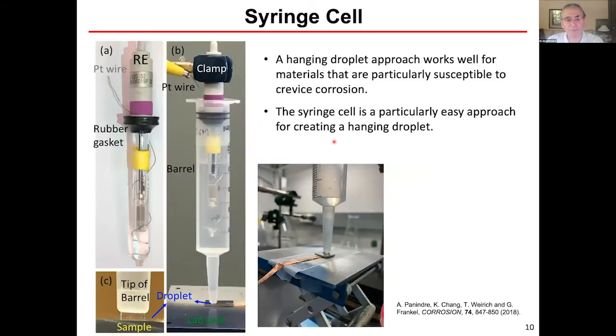One approach that we've taken is the syringe cell. John talked about a droplet cell. This is also work that was led by the efforts of Anoop and published a few years ago. This is a very simple approach to creating a droplet, and it allows you to make very easy measurements in the absence of a crevice, because we just have this droplet you can see here. It's basically a simple syringe where the plunger is removed and the gasket perforated to insert a reference electrode and a counter electrode. And with this lab jack, it makes for very easy measurements.